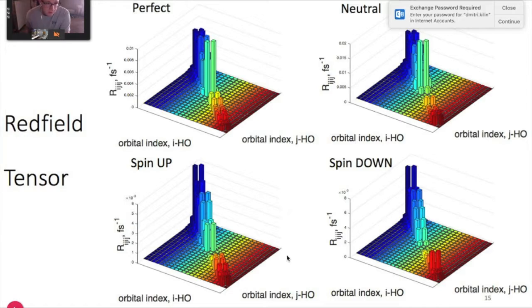But the second thing is that right in the middle of the plot is more or less the HOMO-to-HOMO and LUMO-to-LUMO transitions, which will be 0. And you can see that the relative intensity for the neutral within the conduction band has a yellow and orange peak that are larger than the rest, whereas with the perfect system, it's more uniform. So there's a different coupling with the addition of these states close to the edges of the gap that are playing a strong role, which is what we would expect with new relaxation pathways being opened up with the creation of this state.